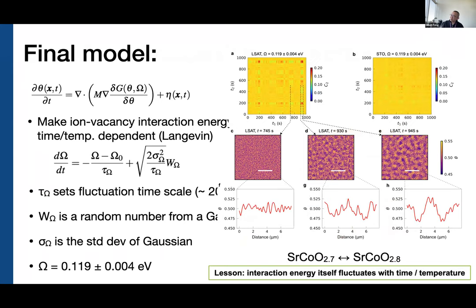But with this final result, they could replicate these two-time correlation maps that I'm showing you at the top right here. The one for LSAT is shown on the left, the one for strontium titanate shown on the right. And because these are simulations, they can show us the real space picture of what's going on.